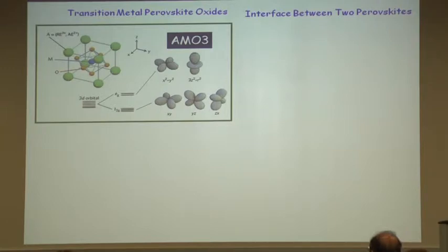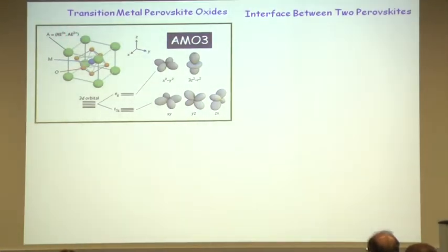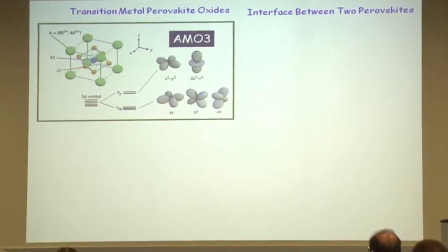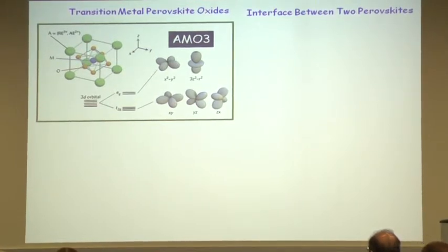All right, let's start with a perovskite oxide, AMO3, where M is a transition metal, and A can be a rare earth or an alkaline earth. And we all know that the transition metal sits at the center of this octahedral cage of oxygen ions. And in this octahedral field, the five-fold degenerate 3D orbital splits into two groups of states. And in the context of this particular talk, these states, XY, YZ, and ZX, T2g states play a very important